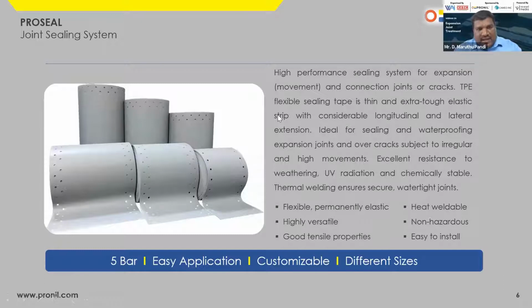and have a better bonding on the substrate. And it has a very good water pressure resistance of 5 bar, is very easy to apply on expansion joints, and is customizable according to customer requirements. We develop products as well as cut and supply the product according to required widths and different sizes like 100 mm, 150 mm, 200 and 300. And it is flexibly elastic, highly versatile, with very good tensile properties, and elongation is very good, both lateral as well as longitudinal. And for overlapping, it is hot welding. We can do overlapping at 340 degrees centigrade, and if there is no movement at all, we can fix it with epoxy adhesive overlapping. Very easy to install.